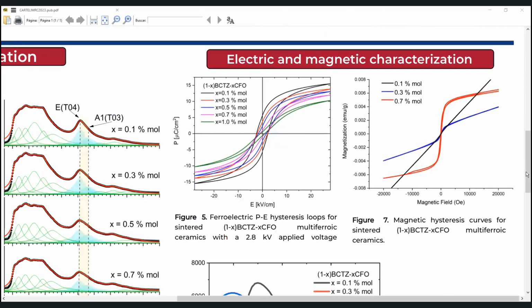In the ferroelectric hysteresis cycles obtained at room temperature, a considerable decrease was observed in the values of maximum polarization and remanent polarization as the dopant concentration increased. These changes can be related to an increase in the proportion of the paraelectric cubic phase of the BCTZ, which in turn leads to a decrease in the proportion of the rhombohedral ferroelectric phase. On the other hand, the decrease in grain size could also be closely related to these changes in the ferroelectric behavior of the materials.